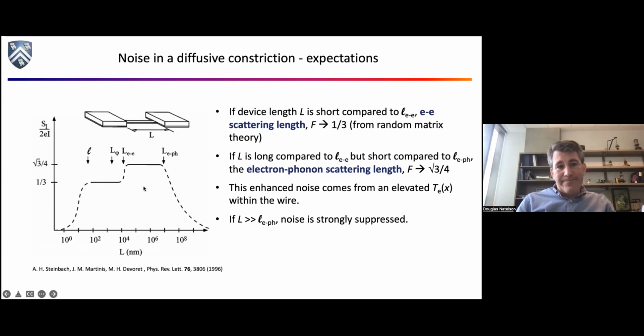So what do you expect to see, right? So this is the Fano factor. It's the noise divided by the Poisson result for a wire, okay? So if the wire is short compared to the electron-electron scattering length, basically the distance scale over which the electrons really bounce off each other and transfer energy amongst themselves, then you're supposed to get a Fano factor in the wire case of 1/3. This has nothing to do with fractional charge. This is just what happens when you worry about scattering off of dirt in a little diffusive system with no energy transfer between the electrons, right?